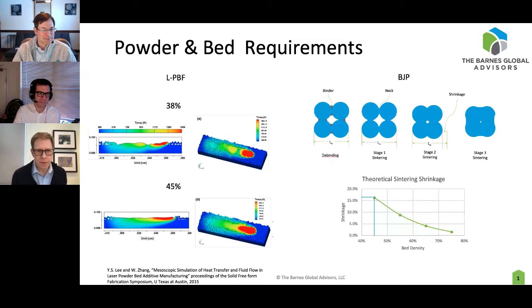So that would strike me as an M&P engineer. I'm looking at this saying, okay, I have a requirement on powder bed processes to hit a minimum powder bed density of 45%. Yep. Beyond that, I probably don't care. It's just more work going into something that I'm probably destroying with laser gas flow interactions anyway. Yep. On the sintering side, on a binder jetting situation, or even with, I'll give our friend Arian at Hollow AM a mention, what kind of bed density are we looking at for binder jetting? Like a minimum, if we wanted to be so bold. 55.